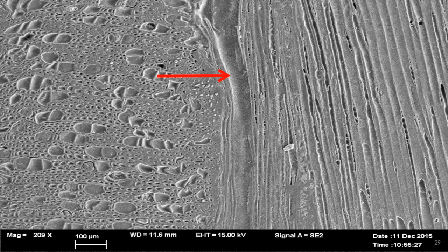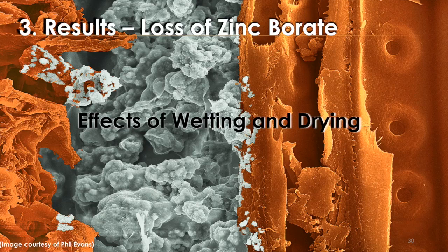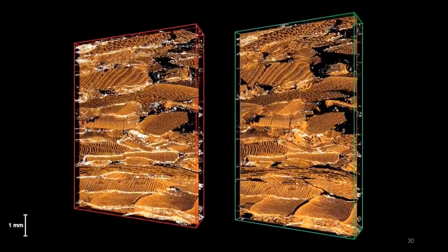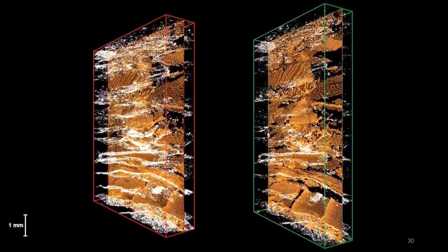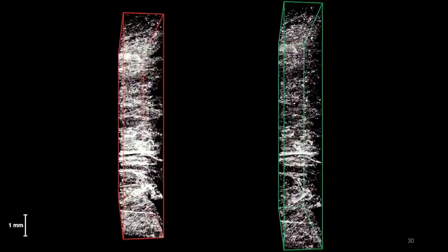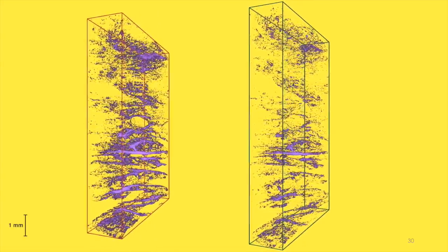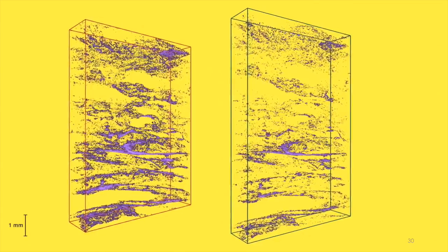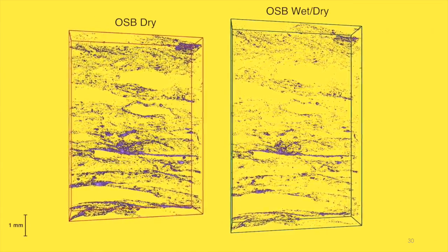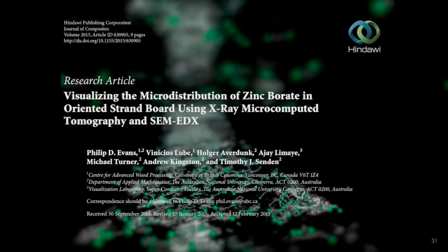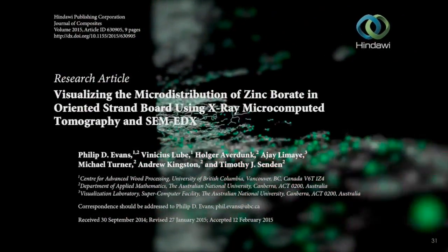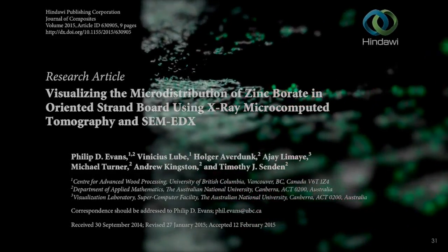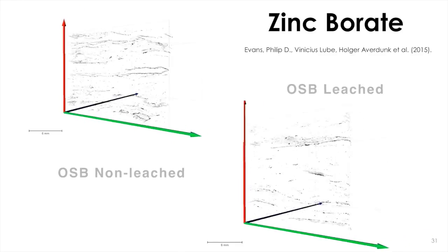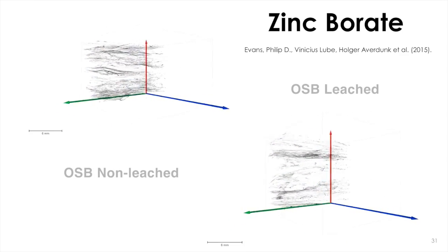Here we can see a long check in the radial surface of softwood. And in terms of loss of zinc borate, note that the wet-dry dataset on the right suggests that wetting and drying reduced the level of zinc in the OSB specimen. However, a 3D network of fine particles of zinc borate remained. These results are in agreement with those from OSB exposed to water leaching published in this peer-reviewed paper which I co-authored, and also presented at the CWPA last year here in Vancouver.